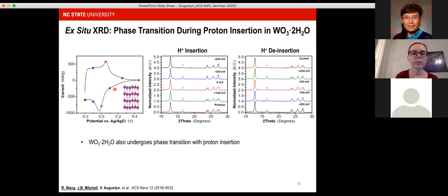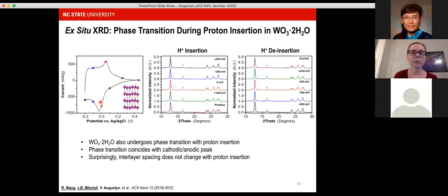What we observed there is that this material also undergoes a phase transition with proton insertion that's tied to these two peaks in the cyclic voltammogram. And what was very surprising is that this first peak here is completely immobile. It never changes. There's no change at all with the proton insertion or deinsertion.